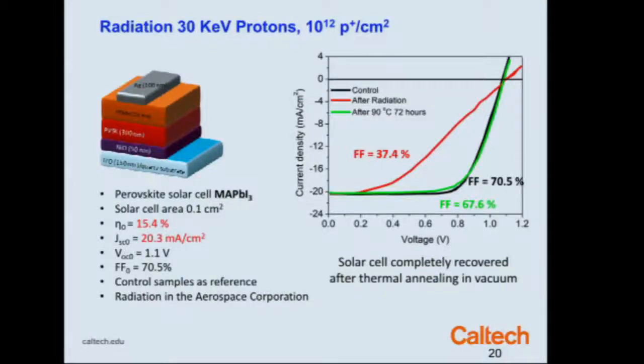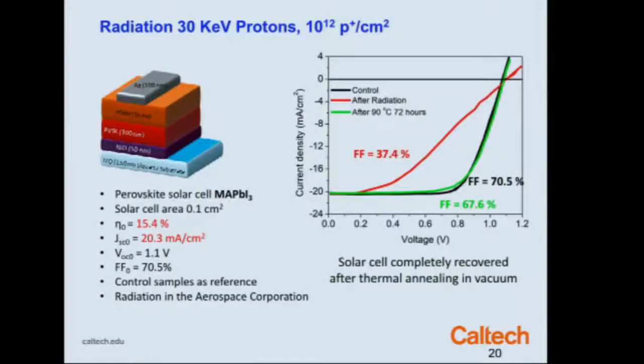That seemingly suggests that there's some series resistance in the cell, in this absorber layer. We think it might be due to proton-induced deactivation of doping, or it may be that it is changing the properties of the interfaces here. Nonetheless, upon annealing at 90 degrees C, and by the way, every time a satellite goes from the dark side of the Earth to the bright side of the Earth, it goes from roughly minus 50 to 100 degrees C or so, so you could think about a low Earth orbit as an anneal cycle. This solar cell recovers its performance completely. So this is a remarkable thing.